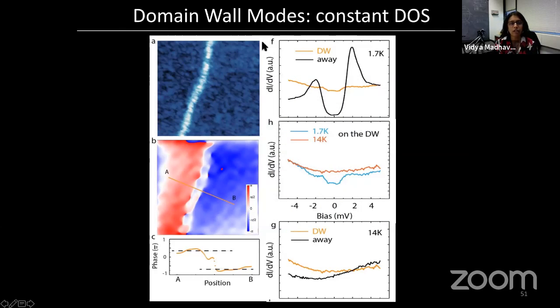So you can ask the question, is this domain wall feature due to the fact that this is an actual crystalline domain wall, and perhaps it's a spectroscopic feature, nothing to do with superconductivity. So we've done temperature dependence. The data I showed you before was at 300 millikelvin. This is at 1.7 Kelvin. You can still see the superconducting gap. It's actually broadened. It's hard to tell one from the other, but you still see this flat density of states at the domain wall.